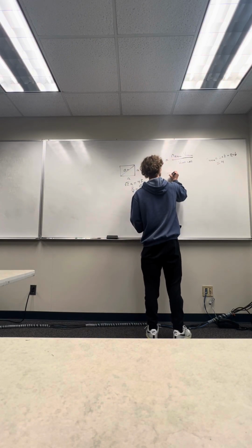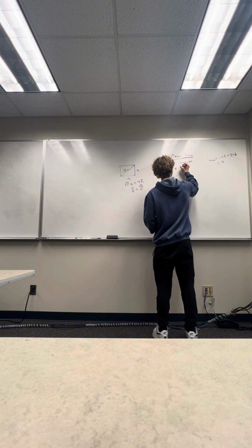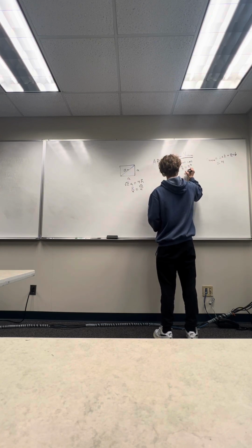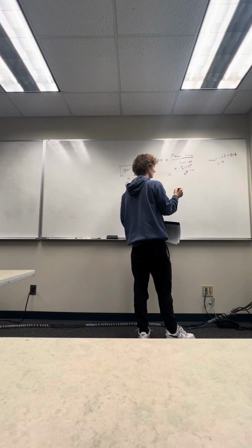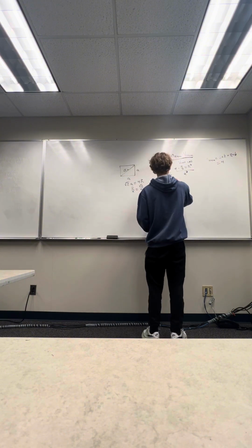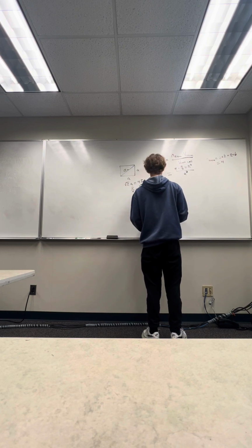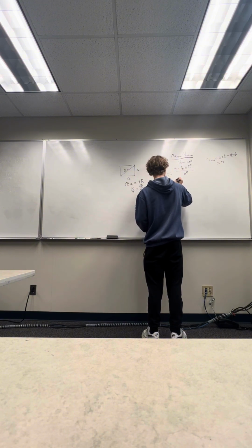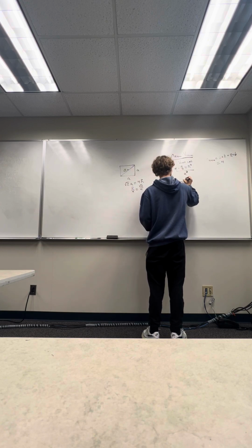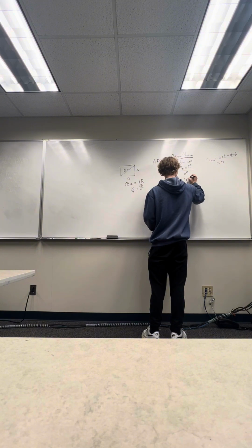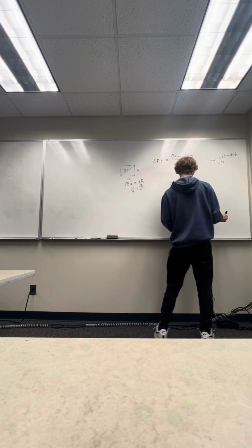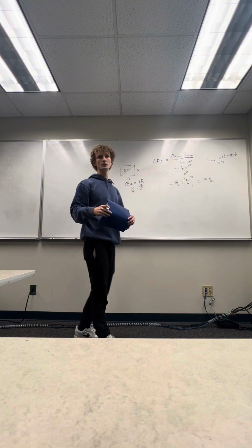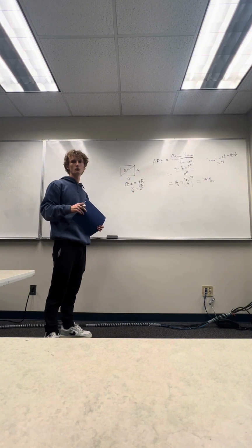So now we can plug in some numbers here. 4 times 4/3 pi r cubed over a cubed, which is the volume of a unit cell. And now we need to get that a cubed into terms of r. And in order to do that, you just plug in radical 2 over 4. So in total, we're going to end up with 16 over 3 pi times radical 2 over 4 cubed. And when you multiply this by 100%, you get 74%. And this is going to be the same for silver and palladium, as they are both FCC structures.